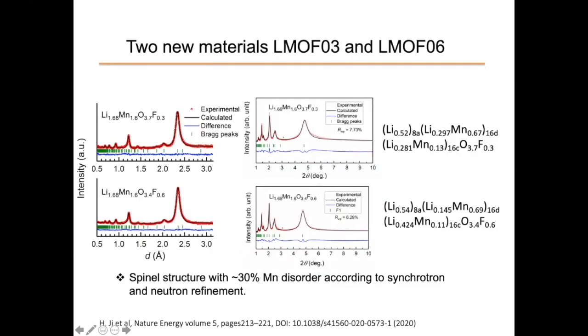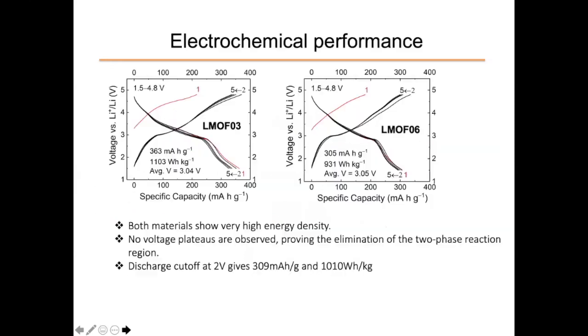You can make these, they do look like spinel. We did neutron refinement on it. And as you can see, this is a partially disordered spinel. The tetrahedral site is partially occupied, about half. But while there is full occupancy on the 16D site, the 16C site is also occupied somewhat. So you do have some cation disorder in this material.